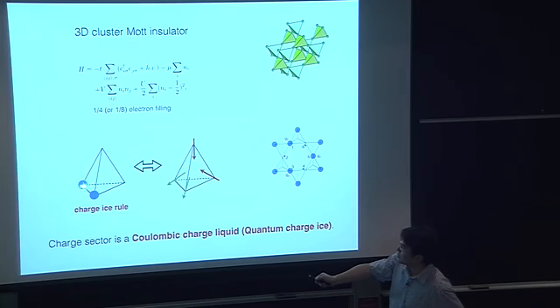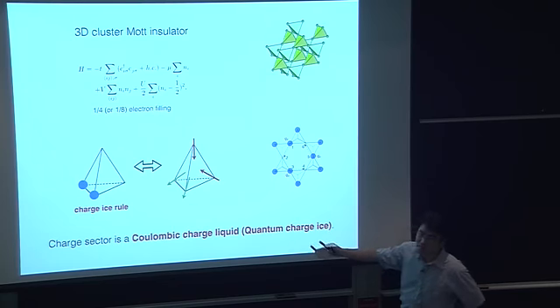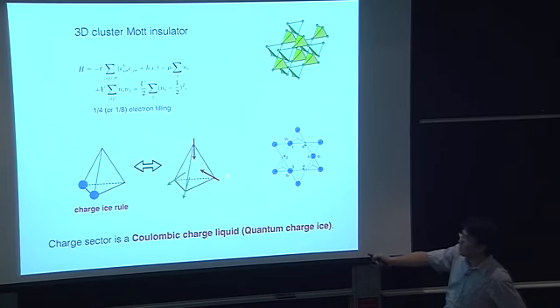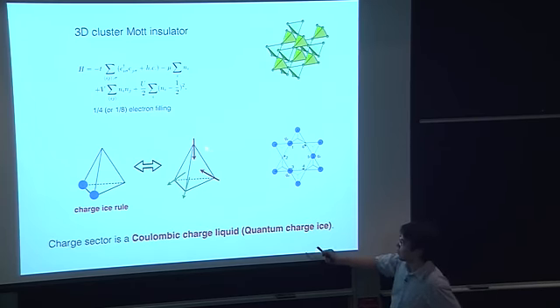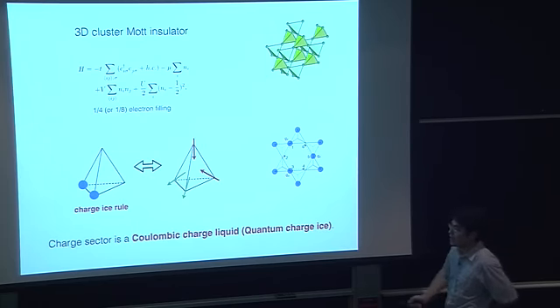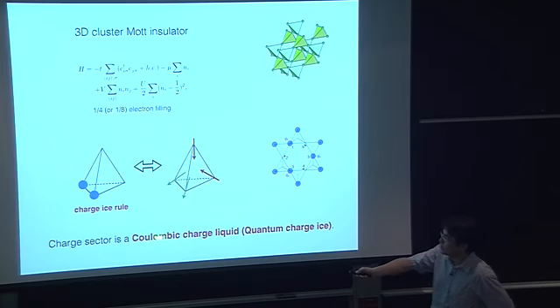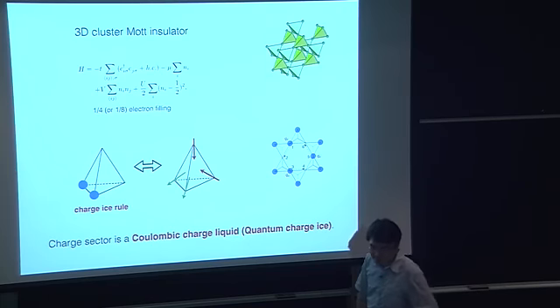If I map an occupied site as a spin pointing out of the tetrahedron, and an unoccupied site as a spin pointing into the center of the tetrahedron, this charge localization constraint will be mapped into a 2-in-2-out spin ice rule. Because the equivalent effective spin Hamiltonian will support the quantum spin ice phase, that means the charge sector of the problem will support the quantum charge ice phase. In other words, the charge sector is equivalently a Coulombic charge liquid. It's a quantum charge liquid.